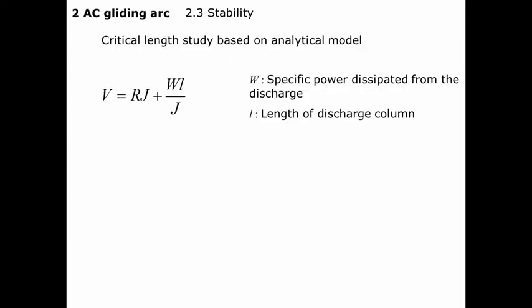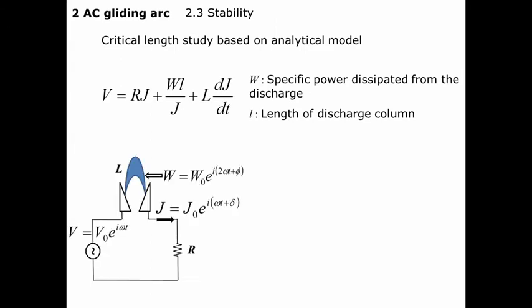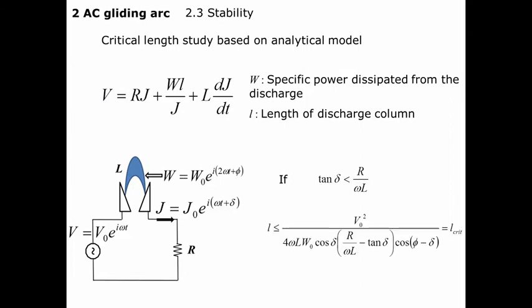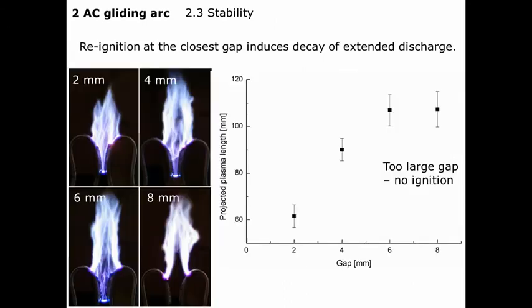Okay, and I think I have to skip this part a bit. I did some stability analysis using a simple model, but probably more importantly, I made some experiments in order to have the longer extension of the plasma, because it's quite useful for treating complicated 3D structures. Then one of the problems of the plasma is that if there's a re-ignition, then plasma can extinguish. So it's nice if we can avoid re-ignition once we have a discharge. So I just physically separated two electrodes to see how it happens, and this is the result.